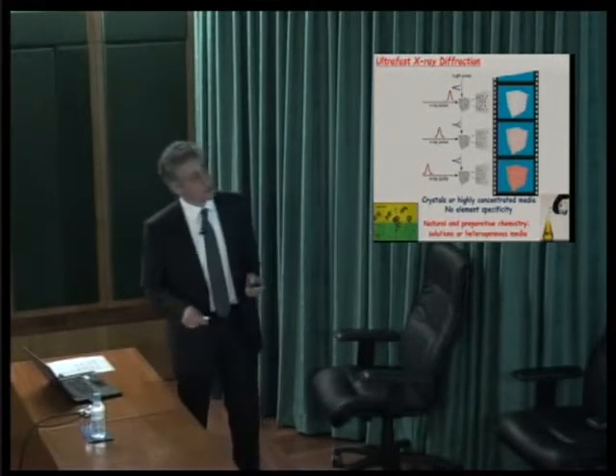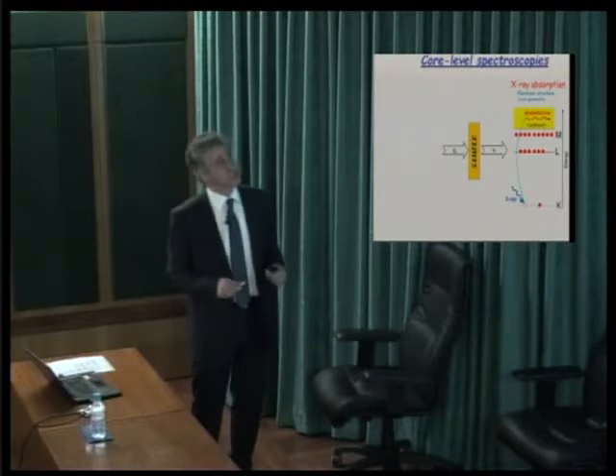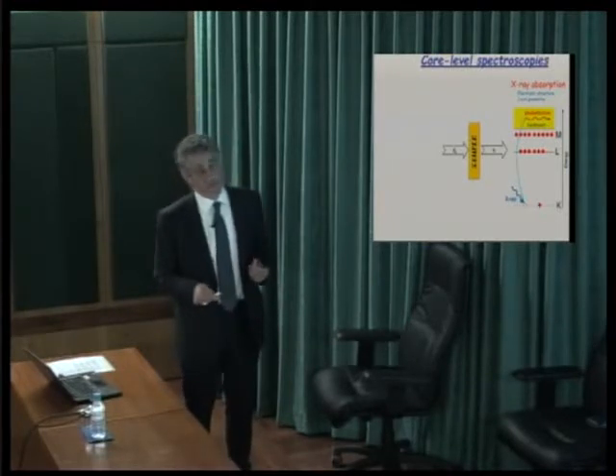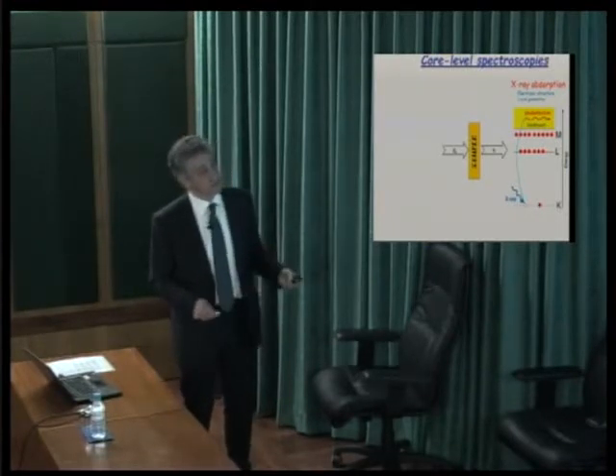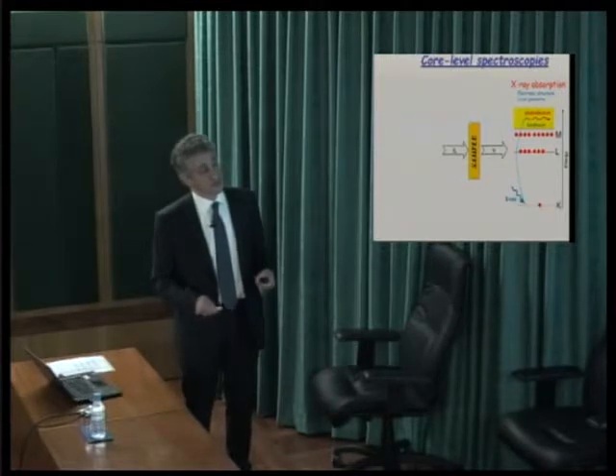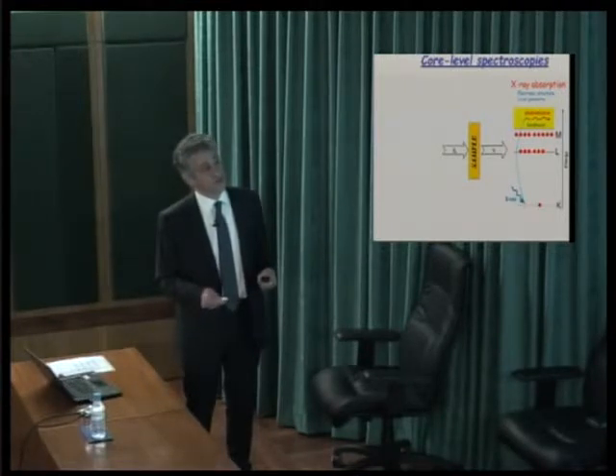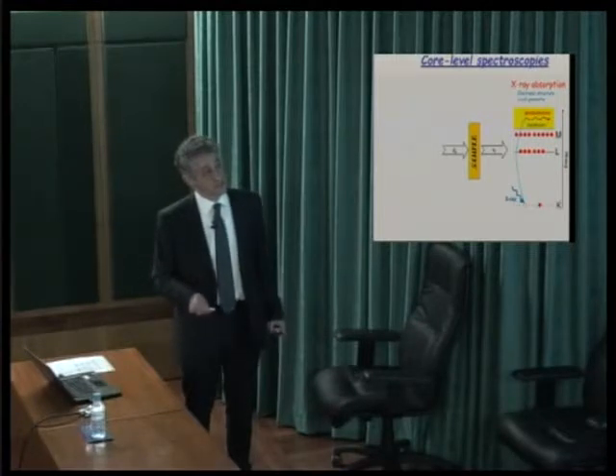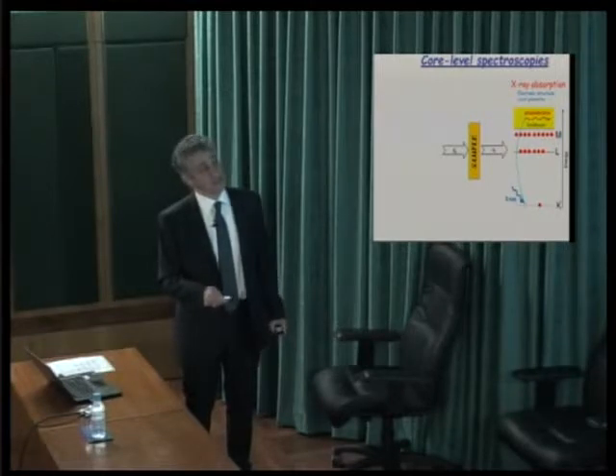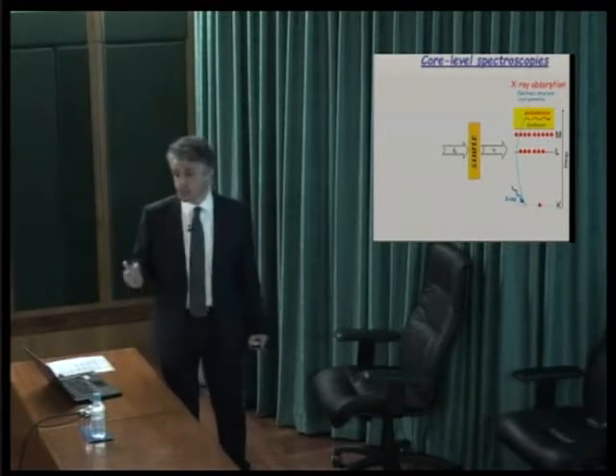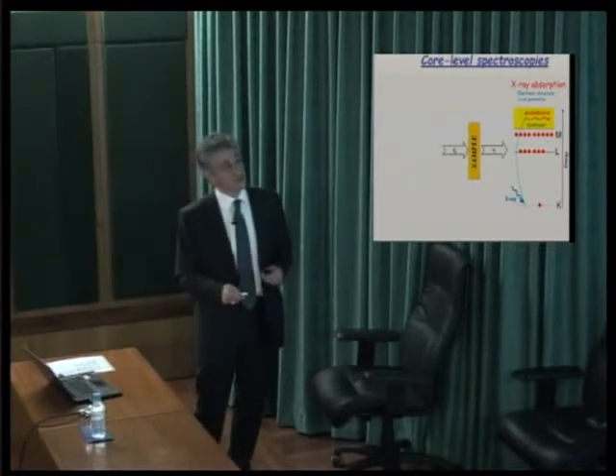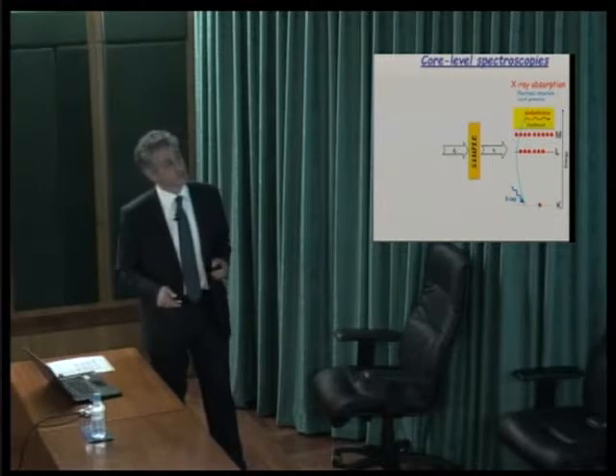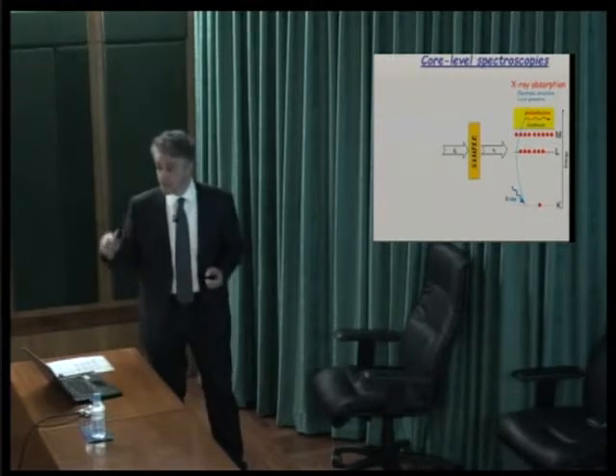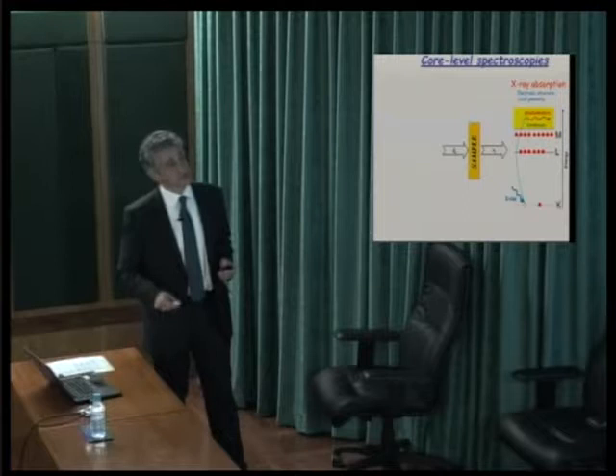So some years ago, we focused on X-ray spectroscopy. And there is a whole bunch of core level spectroscopies that are possible. The most straightforward one is you come with a tunable X-ray pulse and you tune across the ionization limit and you extract an electron from a shell, and that produces a photoelectron, and I will explain to you how you can get electronic structure information, but also the local geometry around the absorbing atom. And this is, of course, element specific, because these are edges, these are transitions that are specific to a given element.